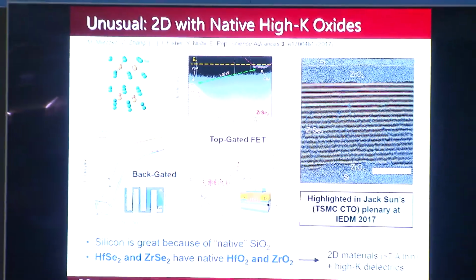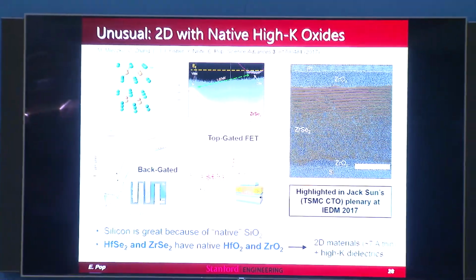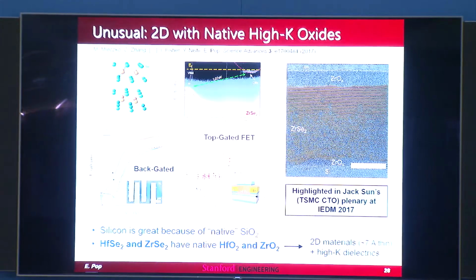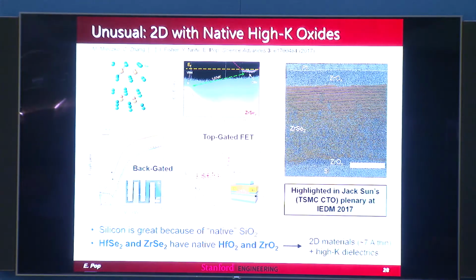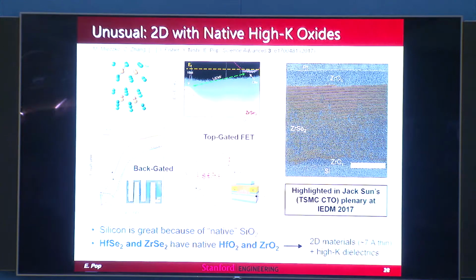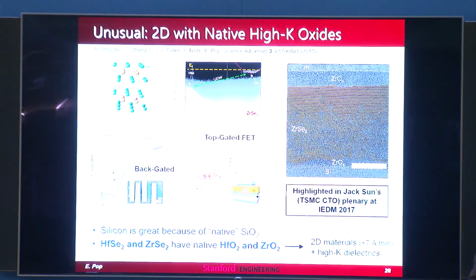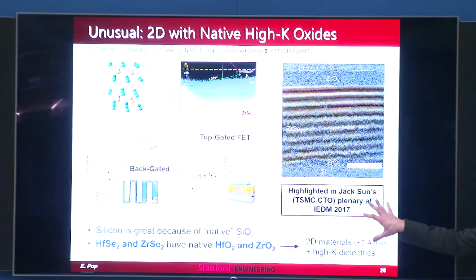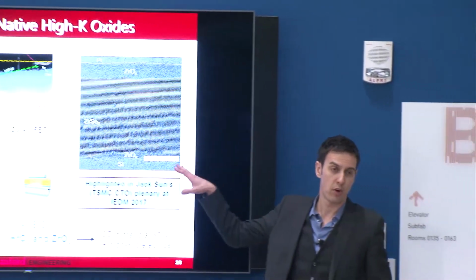Nobody's really made very good devices with these materials, it turns out. Maybe Tomas knows better, I'm not sure actually. But as far as I know the literature, nobody has made particularly good transistors with these materials. The currents are not very high. I believe our best estimated mobilities were less than 10 centimeters squared per volt second. I think the cool thing here is that these even worked with native oxides.